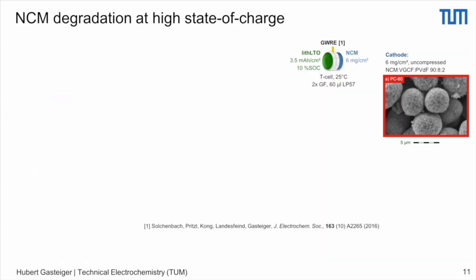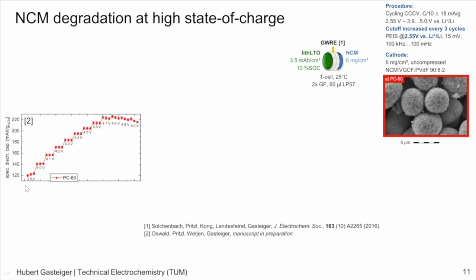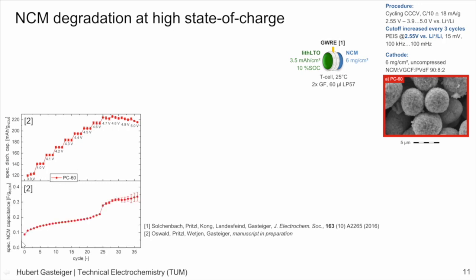And so this is shown here for NCM when we go to a very high state of charge, meaning beyond this 80% SOC, where we know we get oxygen release. This first one here is a polycrystalline material, 622. The experiment we conduct is that we gradually increase the potential in 100 millivolt steps. We measure the capacity, and we monitor the capacitance at the same time. And what we can see here for this material at about 4.6 volts or so, we see a